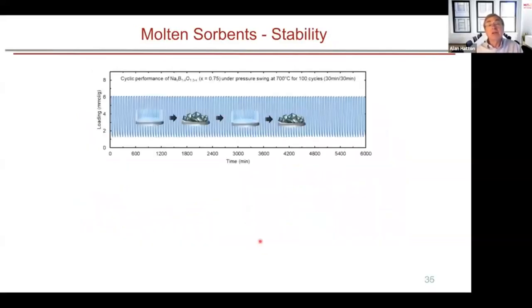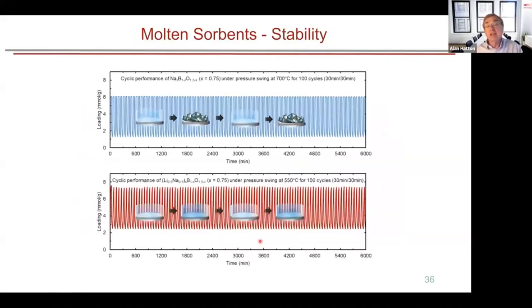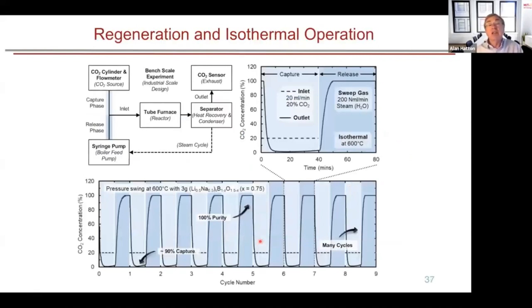So the stability, let me show you the stability for these two systems cycled over many, many cycles, these 100-cycle tests. You can see that there's definitely no loss in overall capacity over this time. They're very stable in these operations. We're able to regenerate these isothermally using steam. So we have an inlet concentration of CO2 coming in. This is when we capture it. And we have a sweep gas coming out, steam in this particular case, to release the CO2 into a steam stream. This is all done isothermally. And we can see that we get very rapid capture and release of the CO2 from these systems.